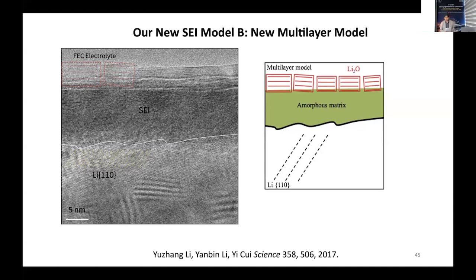So both the multi-layer model proposed by Doron Aurbach and the mosaic model proposed by Peled are right. We have a slight modification. In the multi-layer model here, the inorganic is on the top instead of at the bottom, so it's an inverse multi-layer model. So this is the first time we could clarify the SEI structure.